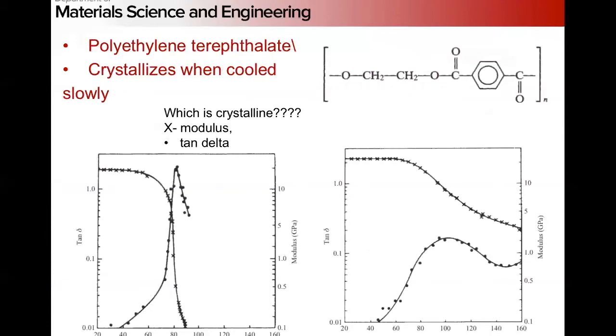Right. So polyethylene terephthalate, this nasty structure here, we've got a benzene, but like a lot of polymers without long, bulky side chains, it will crystallize when cooled slowly. So if we look at these, the x's on both of these curves are our modulus, and the dots are the tan delta, our phase shift from the DMA. Remember DMA, we give it a cyclic loading cycle, and we look at the phase shift between the stress and the strain response. So tan delta gives us an indication of where we have the greatest viscoelastic behavior.